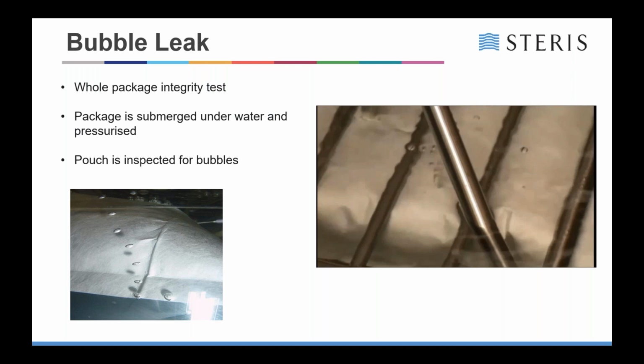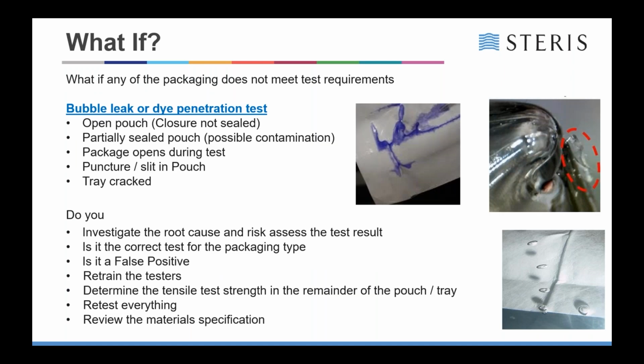The problem happens though when you start to get defects on the side or the seal or through the seal. Are they actual defects, or are they from where the pouch has been folded and creased, which we'll have a look at shortly. Again, if we look at the what ifs, what happens if you have a pouch opening during testing, which does happen quite often. That tells us that the seal is very, very weak and that it wouldn't even pass the likes of a burst test, that its seal strength would be very low.